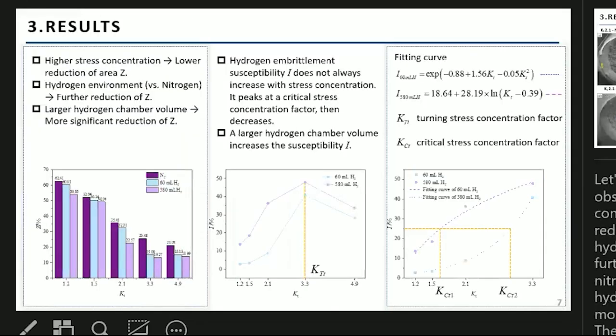First, we observe that a higher stress concentration leads to a lower reduction of area. As expected, the hydrogen environment causes a further reduction compared to nitrogen. And notably, a larger hydrogen chamber volume leads to a more significant reduction. And the hydrogen embrittlement susceptibility doesn't always increase with stress concentration. It actually peaks at a turning stress concentration factor and then decreases. Furthermore, a larger chamber volume increases the susceptibility across all stress concentration factor values.